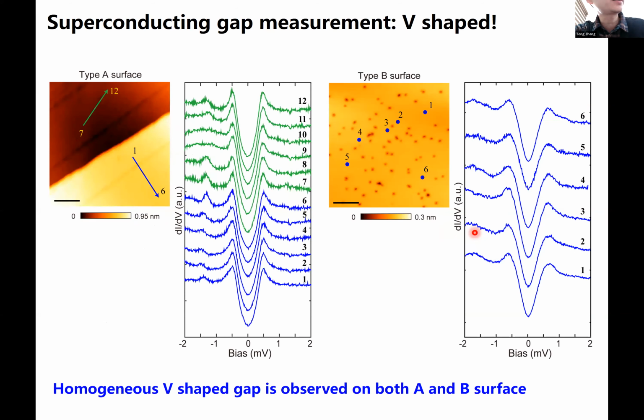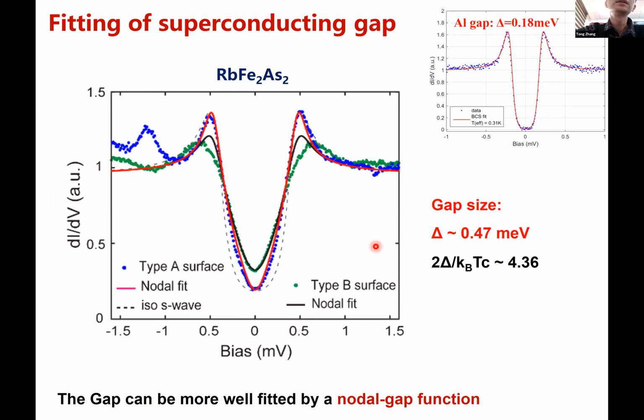Then we check the superconducting gap, and the gap is uniform on the surface, and it's V-shaped. On type A and type B surfaces, they are slightly different. On the type B surface, the gap is a little bit smaller. This shows the fitting of this gap. They are V-shaped, which indicates there are possibly nodes in the gap, or at least the gap should be strongly anisotropic. So we can fit it with a nodal-like gap and get a good fit. If we use the iso s-wave, the fitting is not as good as the nodal one.